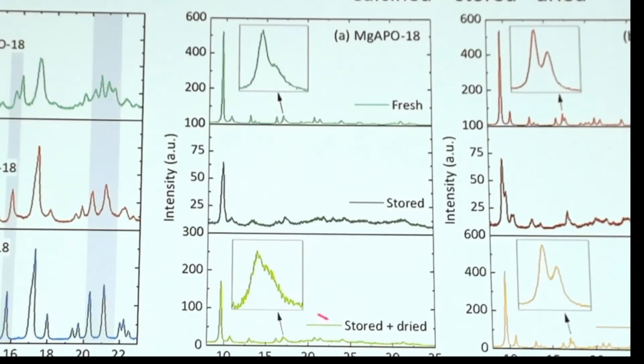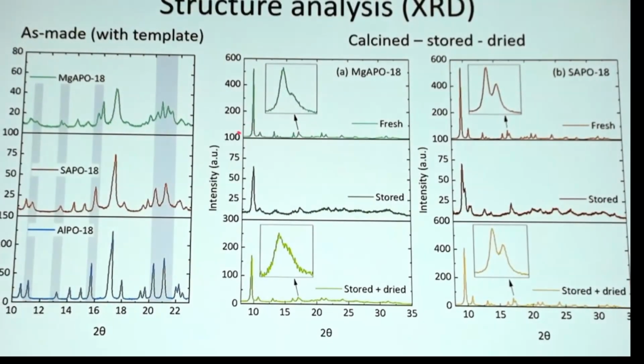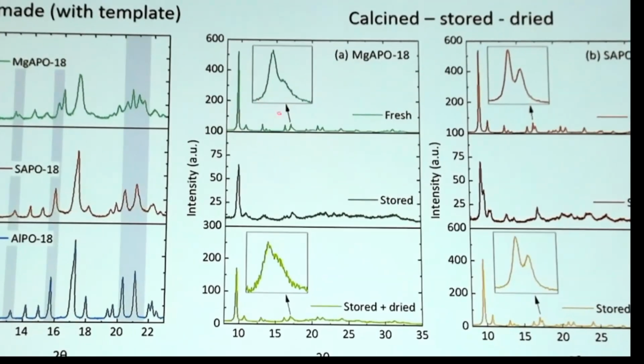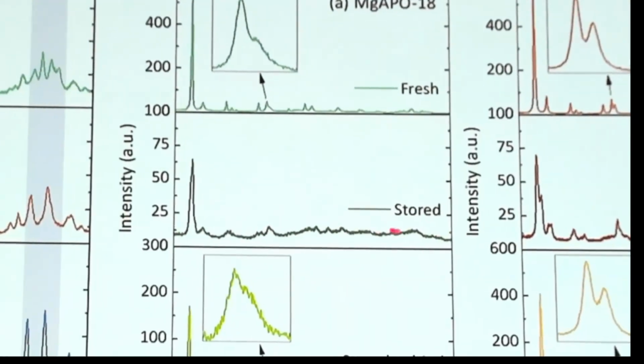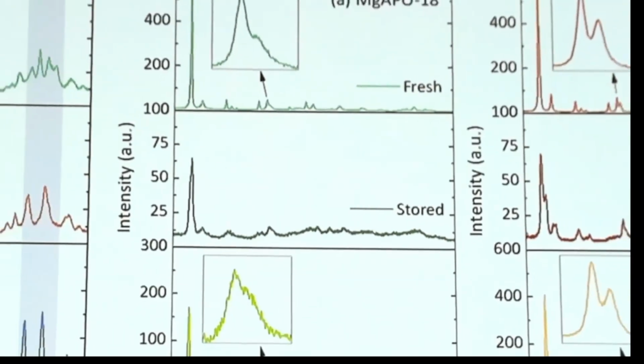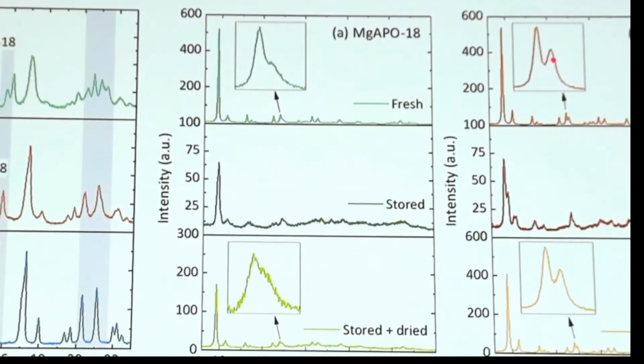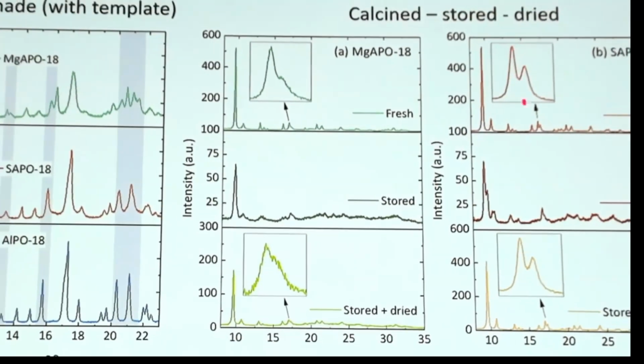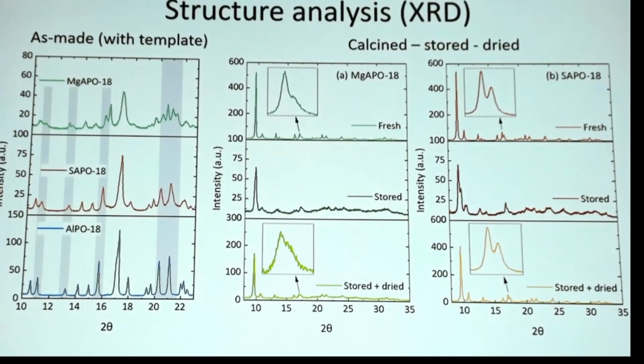But when we calcine the material, most of the chabazite phase seems to collapse. We see here this little intergrown structure still. When we store the material, everything seems to vanish, and when we dry it afterwards, it reappears. We see the same for the SAPO-18 structure, but it seems more stable from this.